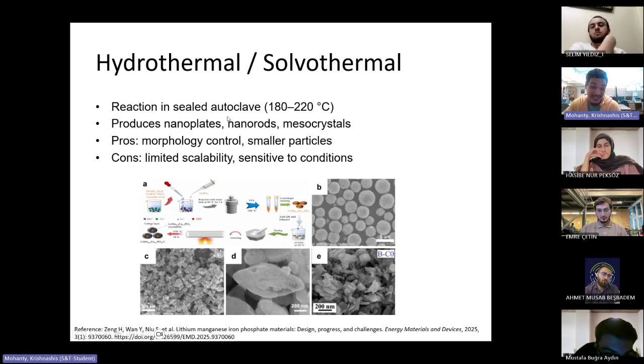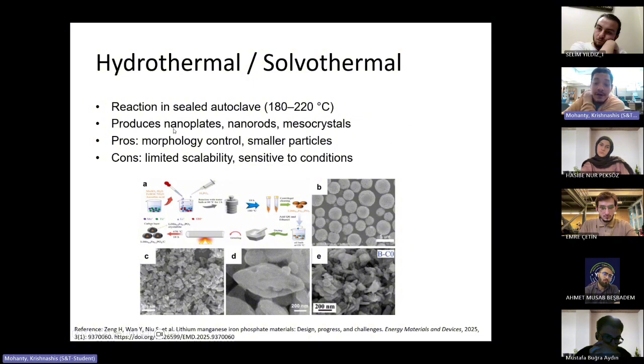And because of the pressure inside the autoclave, it does not have to go to a high temperature. Anywhere around 180 to 220 does the trick. And after we retrieve the autoclave, we get a general solution or a slurry. The advantage of using an autoclave is it gives us a definite particle size. It can morph the molecules of the solution into different shapes. So papers have claimed nanoplates, nanorods, and mesocrystals perform much better than simple chemistry.